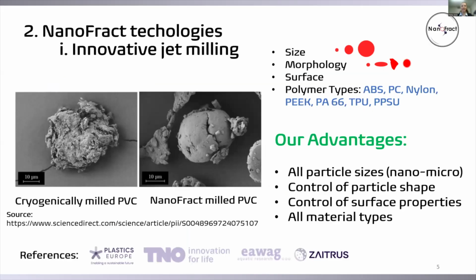This slide shows you the main advantages of our jet milling technology. On the photo, you see, for example, PVC plastic milled by our technology compared to PVC which is cryogenically milled using common ball mills available on the market. And it is clearly shown that the particles obtained by our technology have a more round form and a smoother surface compared to the cryogenically milled particles, which makes them suitable for additive manufacturing applications.